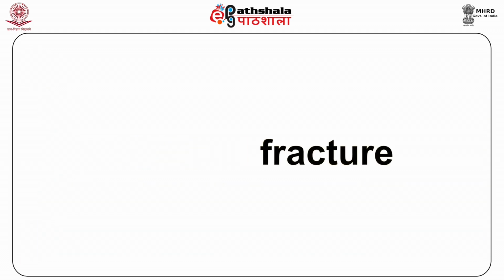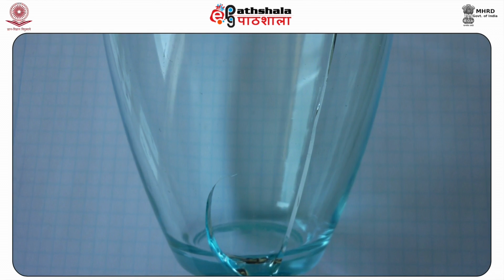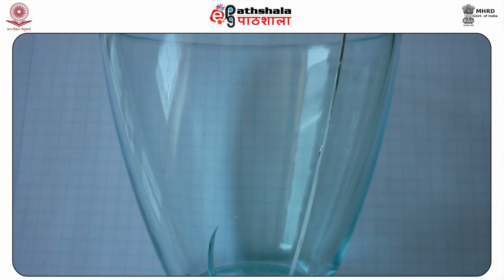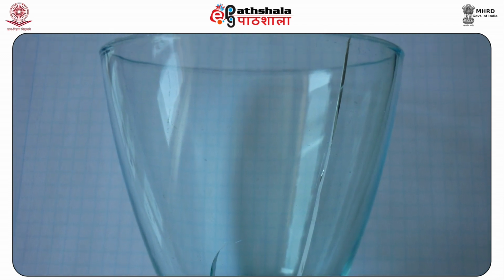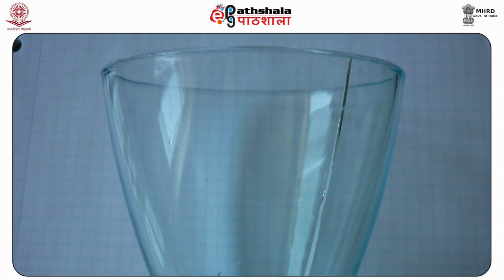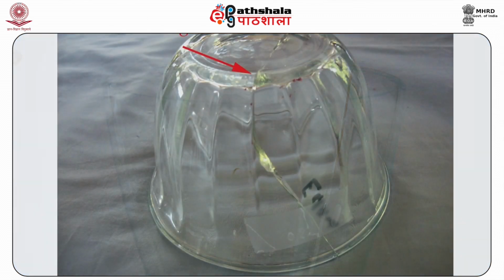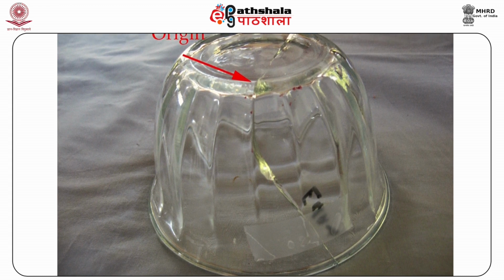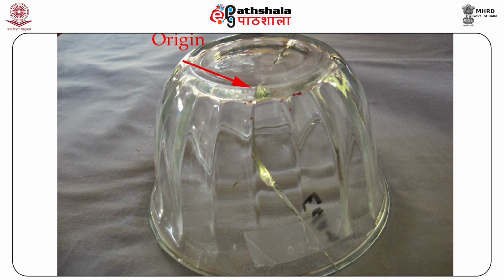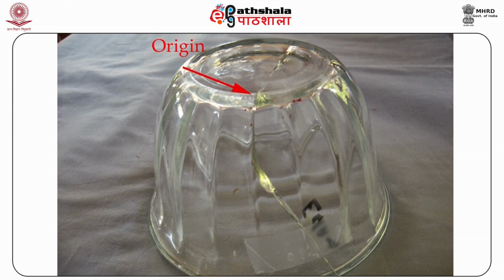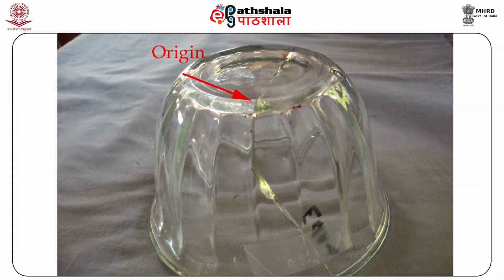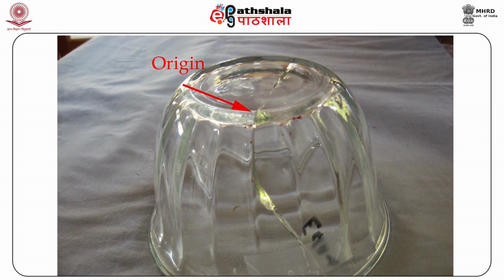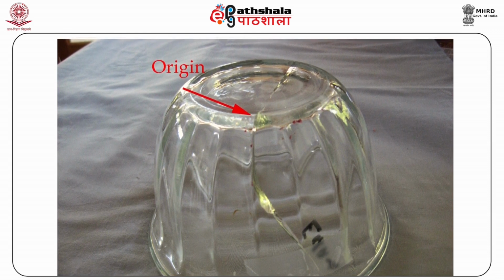Thermal fracture. If very hot liquids are poured into cold glass or very cold liquid is poured into hot glass, a thermal shock is produced, leading to fractures. These occur in the bottom of the container around the circumference with no or very rare surface markings, resulting in fracture perpendicular to the long axis of the container.